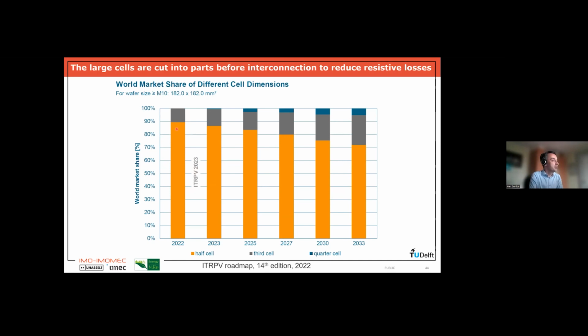So that's why most of the modules that are made today are based on so-called half cells. So what is done? The large wafer is made into a solar cell, but then before the solar cells are put into the modules, they are cut into two half cells. And the half cell, of course, produces only half of the current. And this is a big advantage. You still have the same amount of cells in your module, but by cutting them in half, you reduce the current by a factor of 2, and you gain a lot in efficiency because you have much less resistive losses. And in the future, it's even expected that cells will be cut into even smaller parts, which is already done for the shingling technology, by the way.